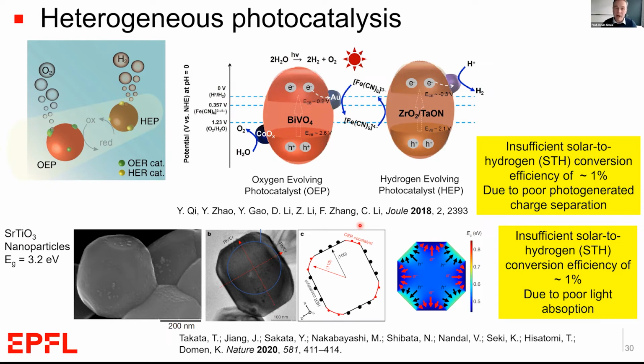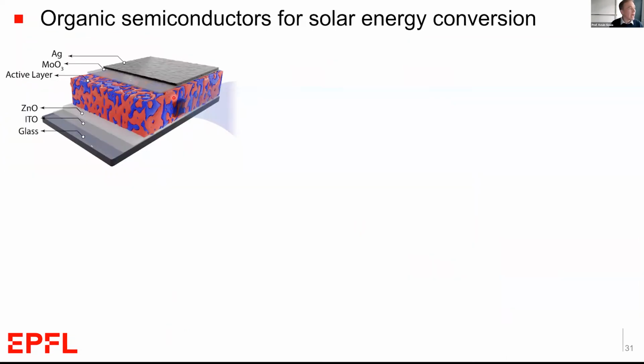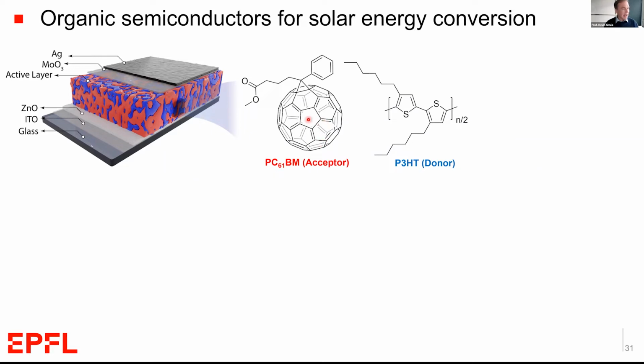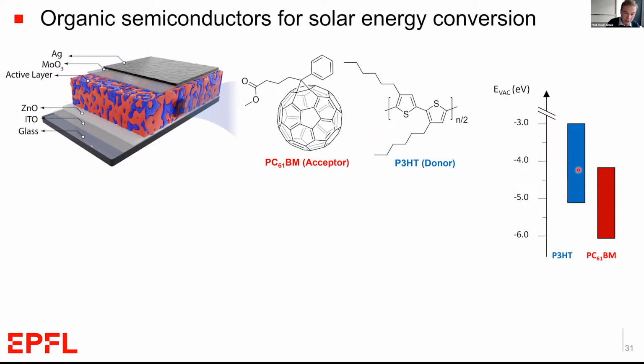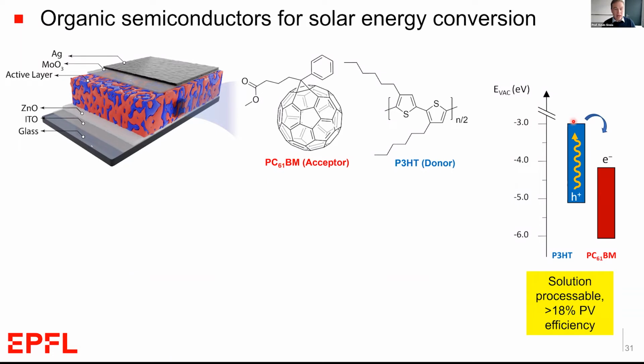In contrast, there is a type of photovoltaic material system that gives intrinsic charge separation on that nanometer length scale, and that's an organic bulk heterojunction. In fact, the material combination of soluble organic semiconductors like PCBM and P3HT has been used in organic photovoltaics now for almost decades. And the interesting aspect of these materials is that upon light absorption, they do not produce free charge carriers. Their dielectric properties require the formation of a heterojunction between, for example, the electron donor and the electron acceptor. Upon light absorption, which creates a bound exciton, if that exciton is in high enough proximity to an electron acceptor, an electron can be transferred from the donor to the acceptor, effectively separating the charges.